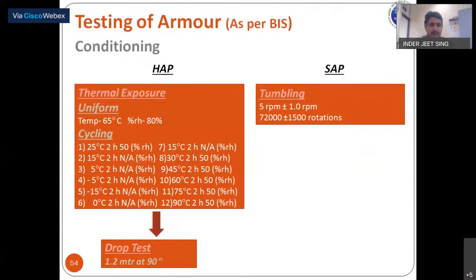So what happens before the ballistic test? It undergoes various other rigorous tests like conditioning. The hard armor panel undergoes thermal cycling, going as high as 90 degree centigrade, and also down to minus 15 degree centigrade. And then there is a tumbling test for the soft armor panel, where in a drum it is rotated for 10 days and in water. After doing everything, they are tested against bullets.